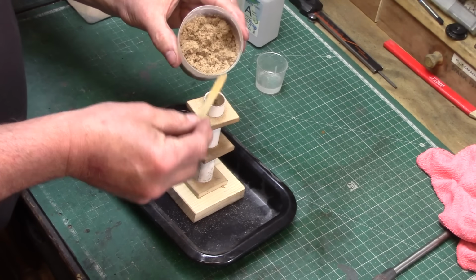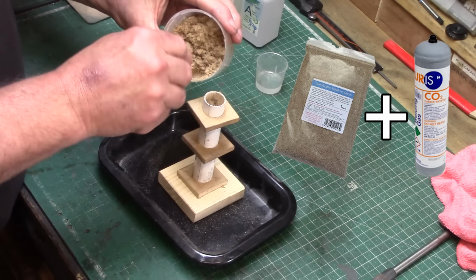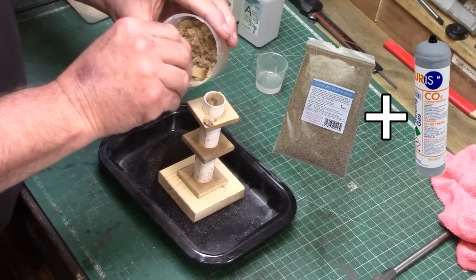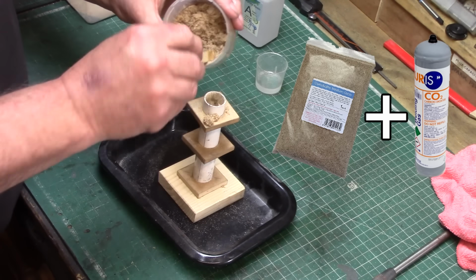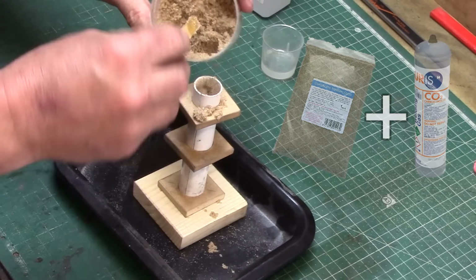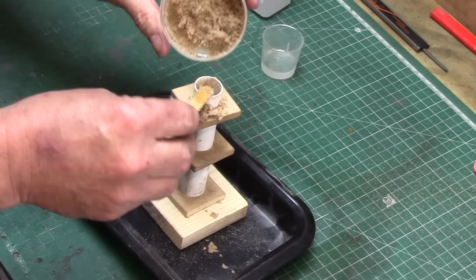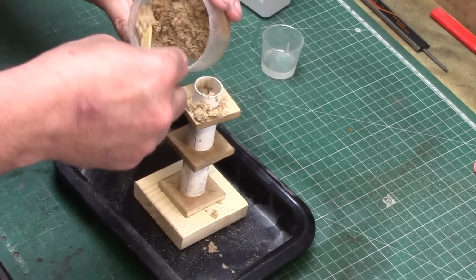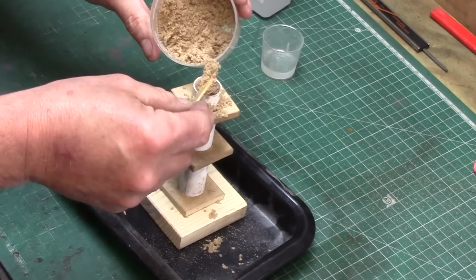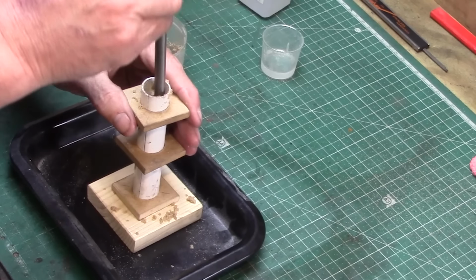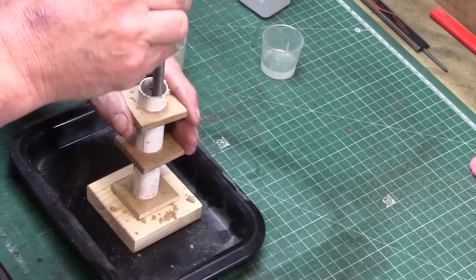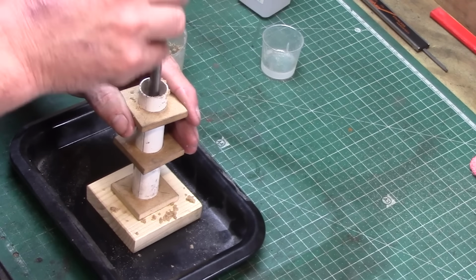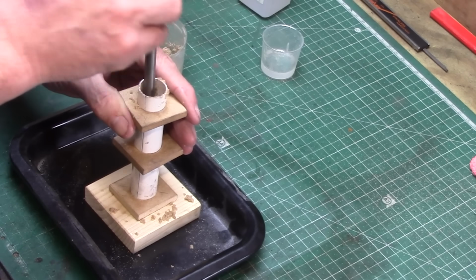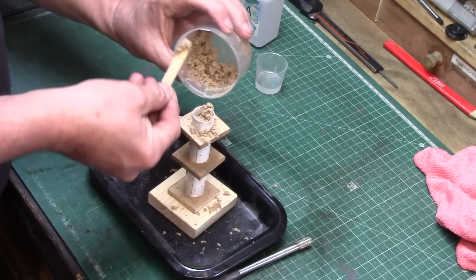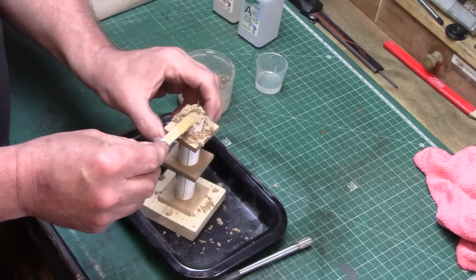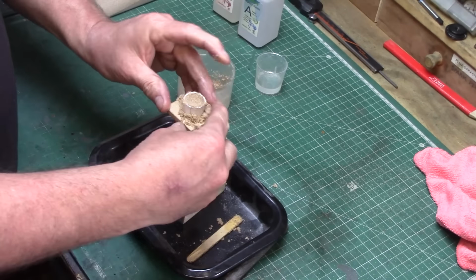Now the usual method for making sand cores is using sodium silicate mixed with the sand and then hardened using CO2 gas, but I don't have this setup, so opted to try the epoxy way. And I find it works well with aluminium at 750 degrees, but not sure how it would perform with higher temperatures such as bronze or brass. And of course the other downside is you need to wait for it to cure before removal.